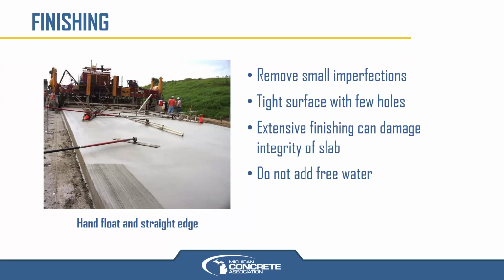It's not really a finishing operation. It's more of a smoothness checking operation, but it does help cut some bumps and find some voids or dips or bird baths. And then bull float. You can see that in the foreground, right near where some of the broom or groove texturing has been put near the edge. So yeah, it's placement, consolidation, strike off, bull float, texture, and cure. Basic. You do not need to get out on knee boards and hand floats and be scrubbing this thing. Just touch it as little as possible. That's what we recommend.